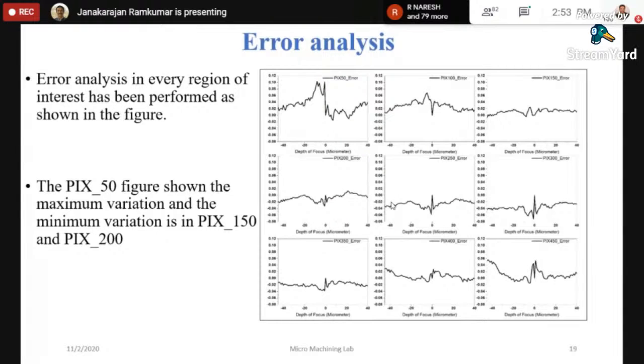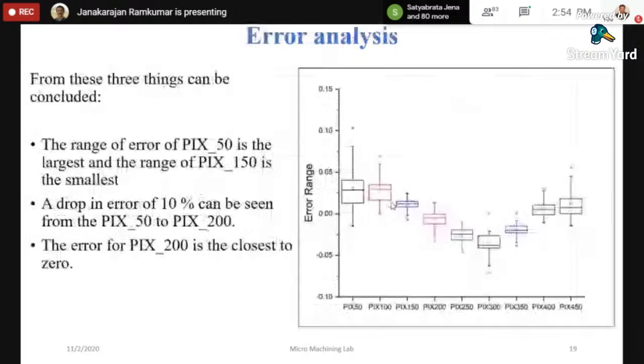Error analysis in every region of interest has been performed. Along a straight line, I took several pixels. The figure shows the maximum variation and the minimum variation in pix 50, pix 150 and pix 200. So we try to get this variation for pix 50, then the maximum variation of pix 150 we got, and then we did this cross correlation. We were trying to do the error analysis.